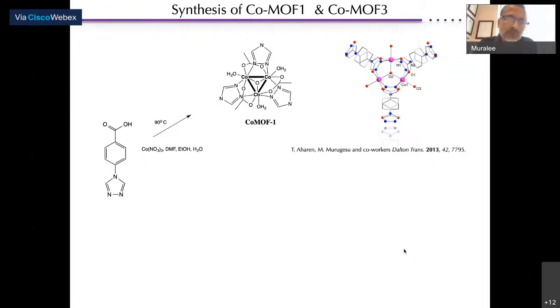So we sought to use cobalt, which is a highly anisotropic metal ion. In this reaction condition, we were able to get these triangular units where you can see the cobalt centers are equivalent crystallographically. Therefore, you have antiferromagnetic coupling also in this system, which leads to a delocalized system in this case. But unfortunately, this MOF wasn't very stable, so it decomposes very quickly.